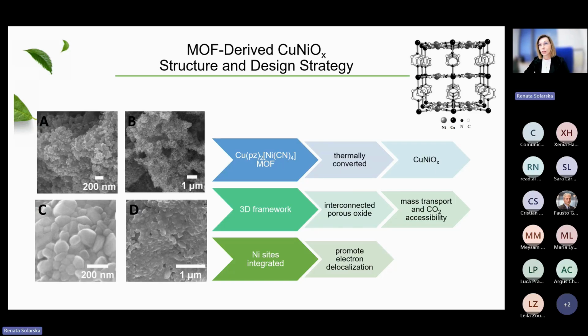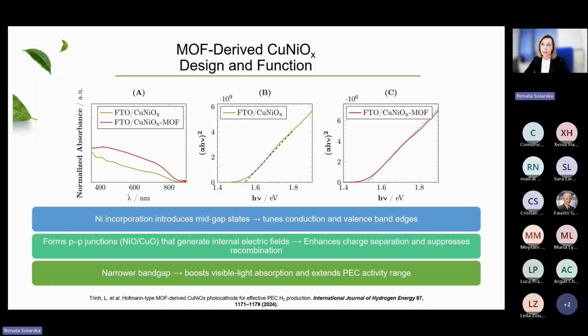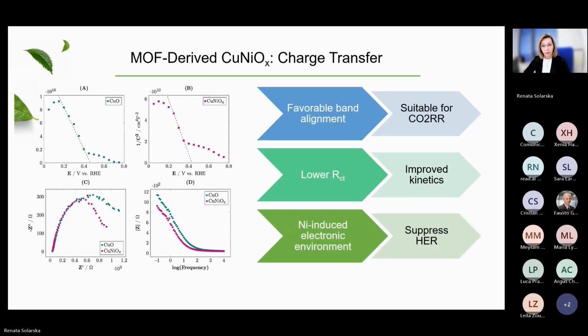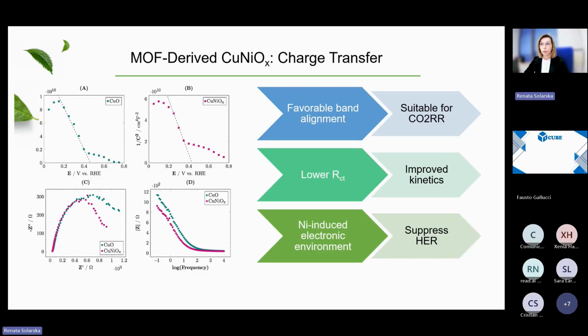And what is even more, by electrochemical approach, we could detect that the nickel introduces mid-gap states, which affect the conduction within the layer and the position of the valence band edges. Here, through the electrochemical measurements, we could check the charge transfer, which has been improved. Therefore, it might be very effective for the production of CO2 reduction products.